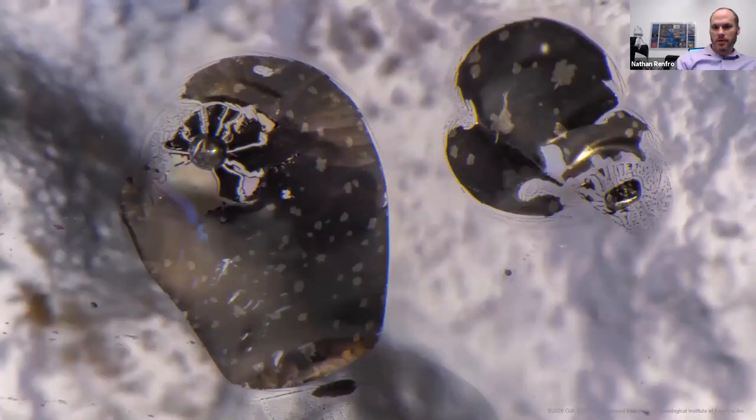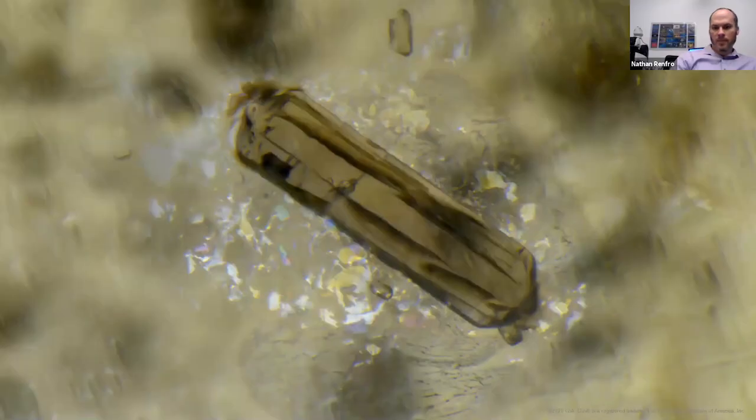Here's an example of metal sulfides from Rock Creek. These are usually really dark. The metal sulfide was confined to a sort of core crystal, and sometimes in the ground the core crystal becomes molten and ruptures, with the contents spilling out into a fracture and leaving a large dark stain in the crack. This is a crystal of clinozoisite, regularly seen in sapphires from these secondary deposits. You can also see a halo of colorful platey features around it — this is sort of an equatorial thin film of fluid inclusions surrounding that clinozoisite crystal.